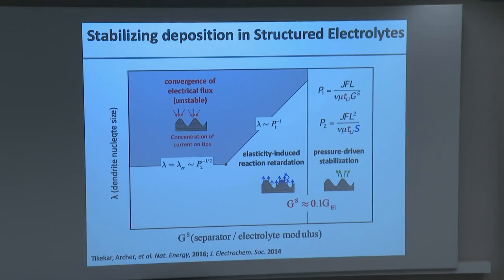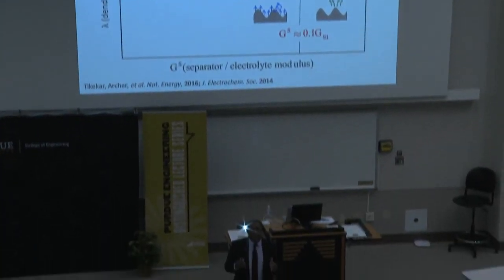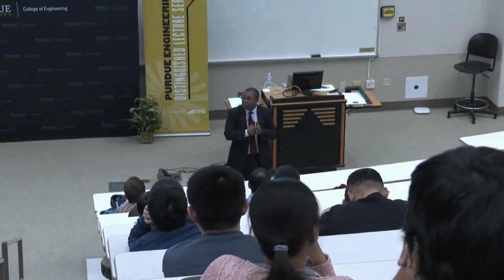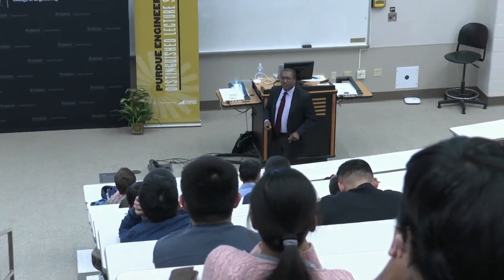Now, what was surprising to us is that by plotting the length scale of the bumps against the modulus of the separator, which enters through this pressure term, we found that you can get stability at any pressure, at any modulus. The field used to think that this is only possible for solid-state electrolytes, where the modulus of the electrolyte is bigger than the modulus of the metal. In other words, if the modulus of your separator or electrolyte is larger than the modulus of the metal, the bumps just can't grow through it. What we're saying here: not true.